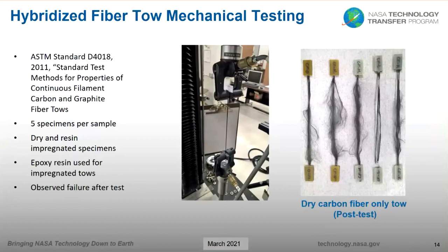So to determine if there was any benefit to making a braid made of a hybrid tow of carbon nanotube yarns and carbon fiber, we first measured the tensile properties of the fiber tows according to ASTM standards. And we measured the mechanical properties of 5 specimens per sample. I believe the ASTM standard calls for maybe 4 specimens per sample. But the ASTM standard also calls for infiltrating the tows with resin and then curing it prior to mechanical testing.